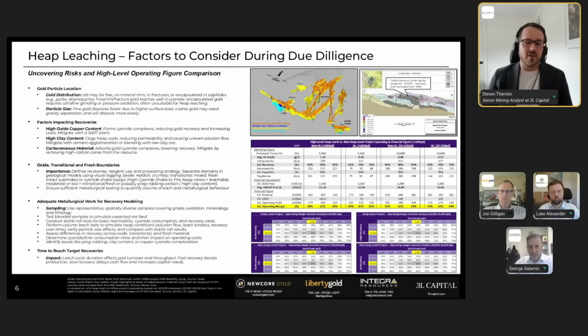Things that can impact recoveries: high copper can cause issues. You can form stable cyanide complexes, and that reduces the cyanide available to leach gold. That can lower your recoveries, but it can also be mitigated with what's called a SART plant. High clay content can be an issue, but that can be overcome, like I said earlier, with agglomeration or a good blending strategy with low clay ore. Carbonaceous material can also be an issue, so it adsorbs gold cyanide complexes, preventing recovery. What you can do is domain those zones out of your geological model to keep this material off